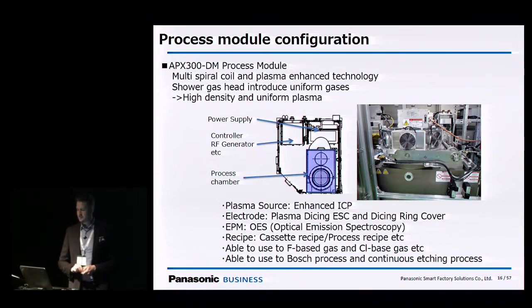So if we take a deeper look inside the machine, we'll go into a little bit more detail in the next slides. So our plasma source is an enhanced ICP. We have integrated endpoint monitoring, so the machine can tell the different layers of the wafer, and also importantly, once the wafer has finished being diced, then dicing should stop. Recipe, it's possible to program the machine to handle multiple recipes for different wafers, or also from cassette to cassette. We can offer fluorine-based gas or chlorine-based gas etching. And typically, most of the time, we're using the Bosch process to etch.